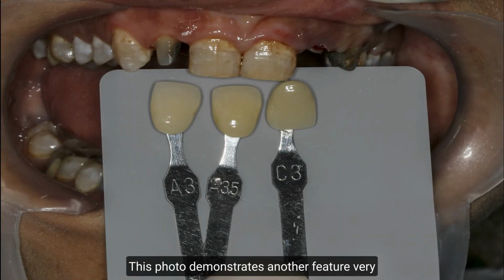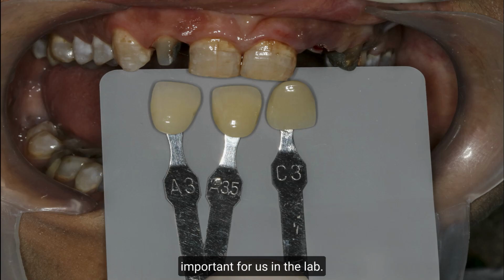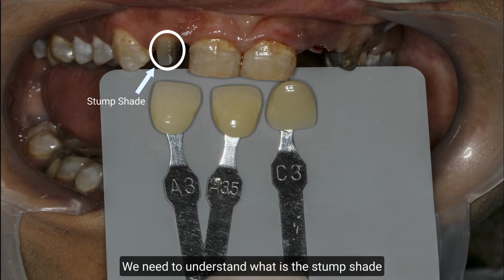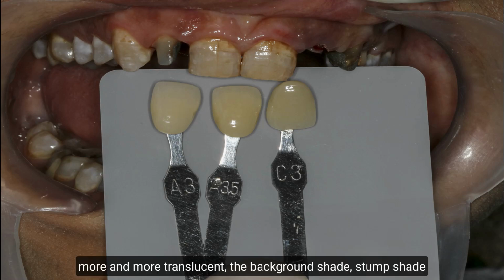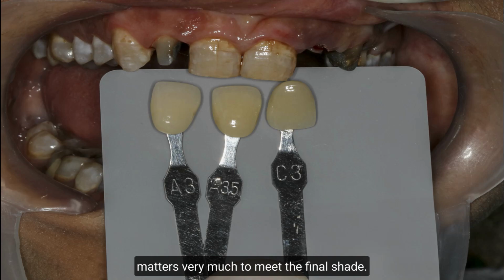This photo demonstrates another feature very important for us in the lab. We need to understand what the stump shade is. With materials becoming more and more aesthetic, more and more translucent, the background shade, the stump shade, matters very much to meet the final shade. So he always tries to give us the stump shade. It is also very important that we don't have any reflections that cover the entire tooth. A small spot is fine, but there should not be a reflection of light over the entire surface.